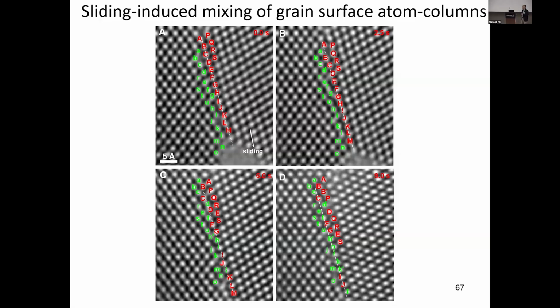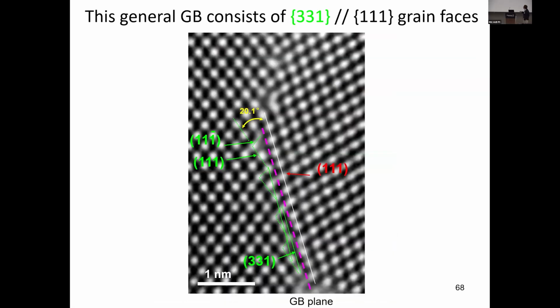So what's the implication of this mixing? Actually, it represents the transfer of atom columns from the surface of the left grain to the right grain. However, this occurs at only room temperature. So this is a deformation experiment at room temperature. At higher temperature, through diffusive processes, this kind of phenomenon is expected. However, now at room temperature, we directly observe this mixing, the shear-induced mixing. Actually, it's facilitated by the pentagon structural unit.